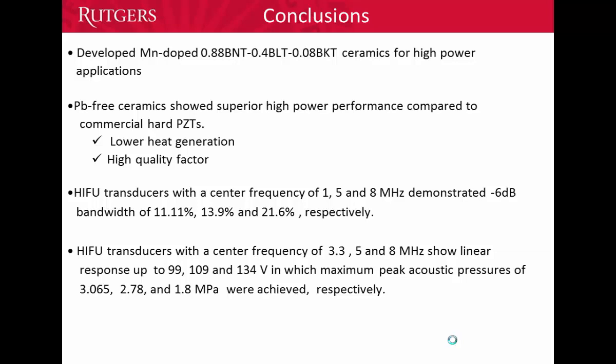We also measured the bandwidth for the HIFU transducers. It's 11.11, 13.9, and 21.60% respectively. And HIFU transducers with center frequencies of 3.3, 5, and 8 megahertz show a linear response up to 99, 109, and 134 volts, in which maximum peak acoustic pressures of 3, 2.78, and 1.8 megapascal were achieved.